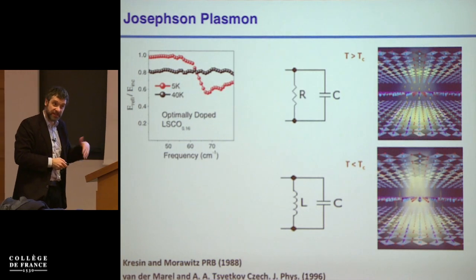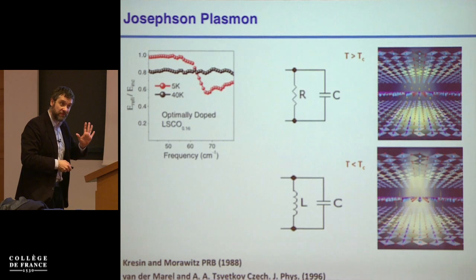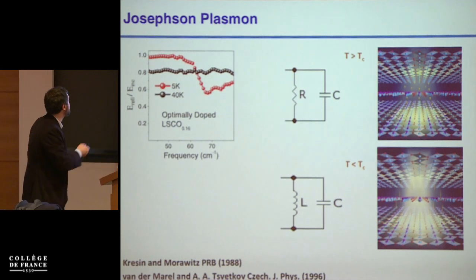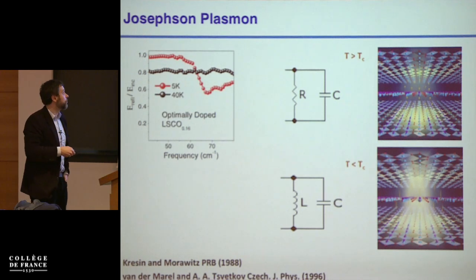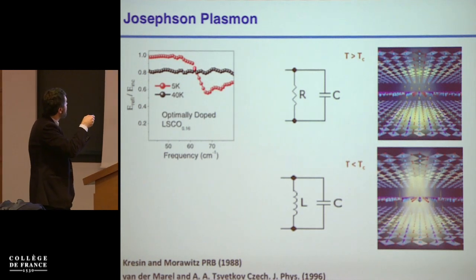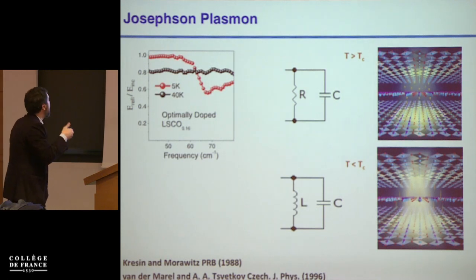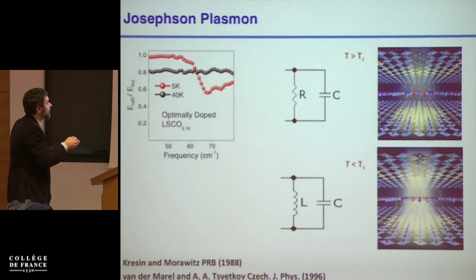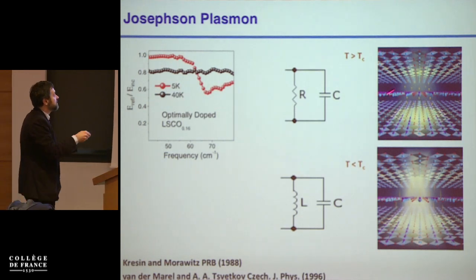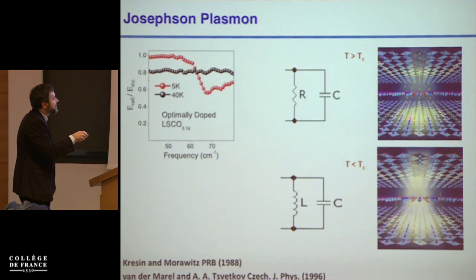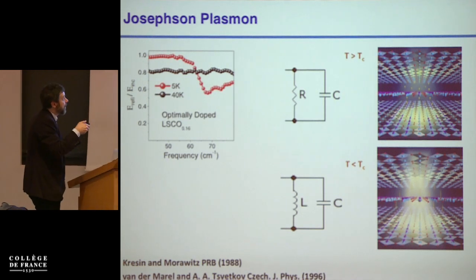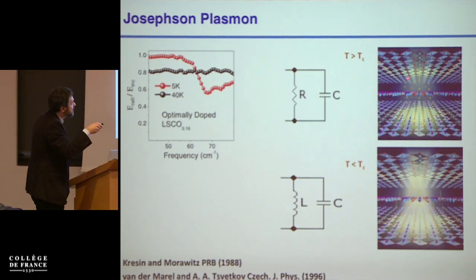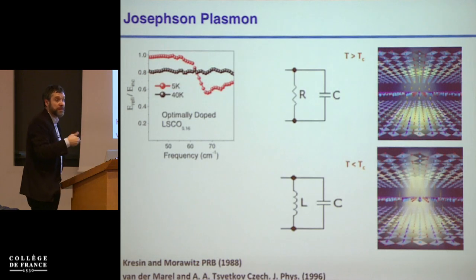This is something that was the subject of the last lecture, but I will just briefly recap what the presence of this Josephson plasma edge tells me about the superconducting state in cuprates. If I measure the terahertz reflectivity with an electric field perpendicular to the planes in cuprates, what I will find is that in the normal state, if I think about these planes, these are the copper-oxygen planes, the way I can think about the electrodynamics at these frequencies is one in which I have capacitances in the plane and resistive transport between the planes.